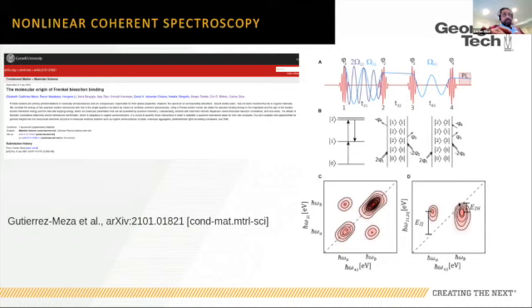But if I see a peak that is below the two-quantum diagonal, it is an attractive interaction. The energy of the two-quantum state is lower than twice the energy of the one-quantum state. Whereas if I see a peak that is above the two-quantum diagonal, then it costs me energy to have that two-quantum state. I get two excitons that I correlate, and the energy of that state is higher than twice the energy of the one-quantum state. These are the signatures that I'm looking for.